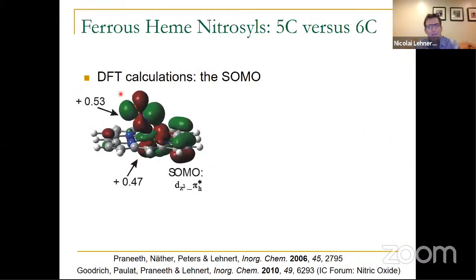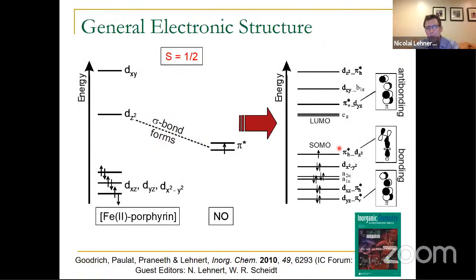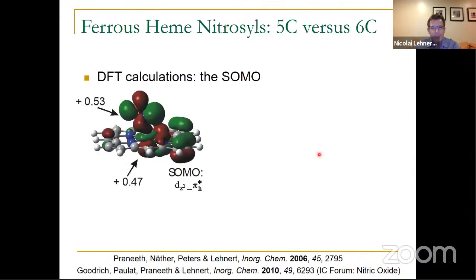So you can see that we have a very strong bond. This is the pi star orbital of NO. Here's NO, here's iron. This is the dz square orbital, and we get a very strong bond. And that unpaired electron, this orbital is occupied with one electron. That electron is fully delocalized over the iron NO unit. So this orbital is essentially 50% iron, 50% NO. And these are the spin densities, so spin is about 50% on iron, 50% on NO.